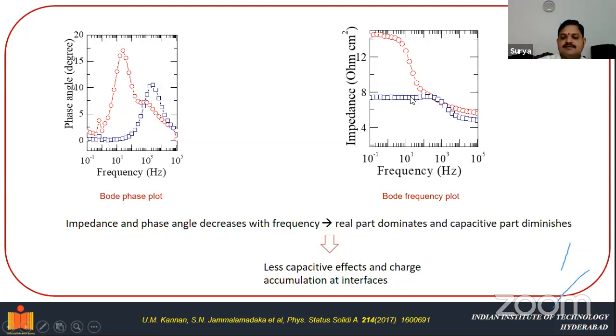What is meant by diminishing of the capacitive part? If the capacitance of the device is more, it means that more charge will be accumulated at one place without flowing. If the capacitive part decreases, that means the flow of current is more, without accumulation of the charges. So there are less capacitive effects and less charge accumulation at the interfaces. If you have more capacitance, the charge accumulation will be more. If you have less capacitance, the flow of the electrons will be more. Since the imaginary, or capacitive, part decreases, more charge flows within the device.